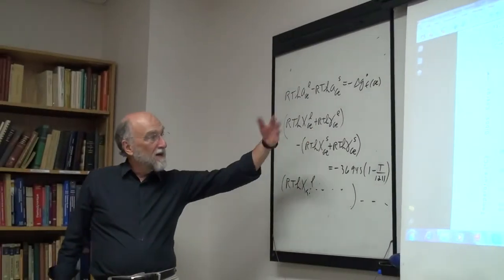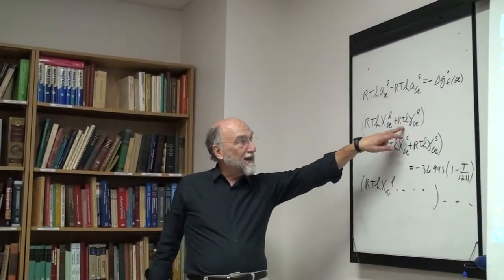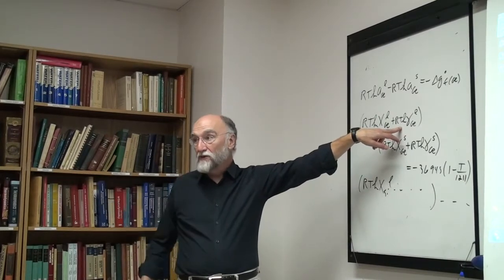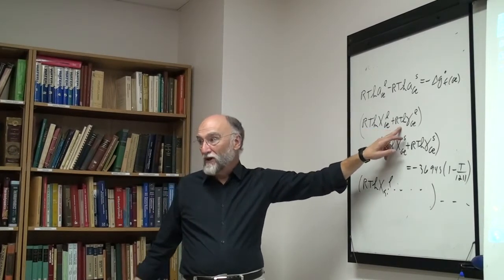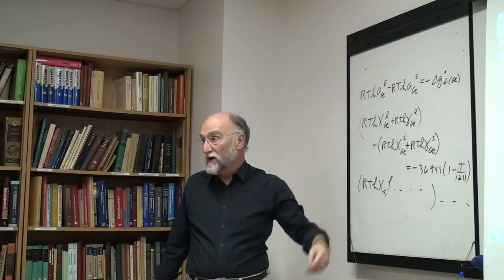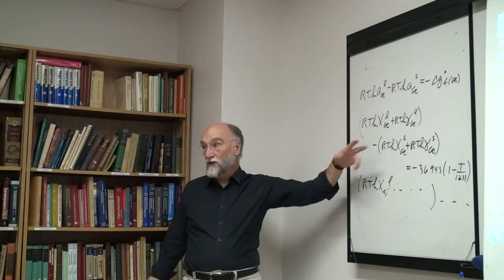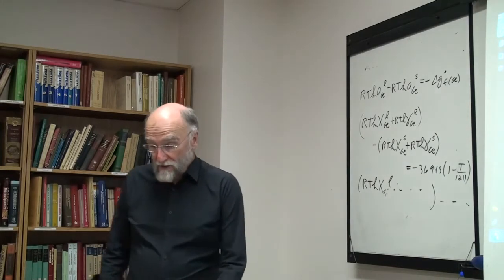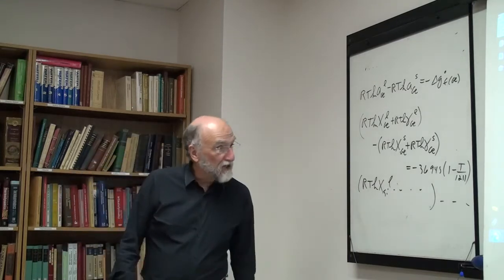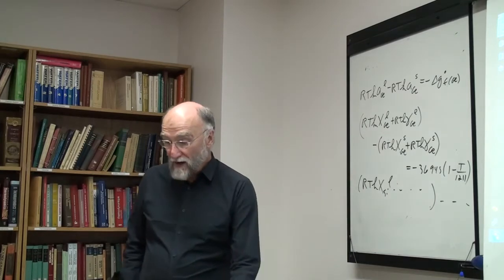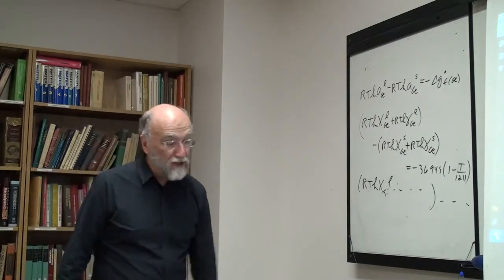The RT log gamma, which is the partial excess Gibbs energy, could be expressed as a power series, a normal polynomial or something, and then you'd have to solve these two polynomial equations in the mole fraction. You could solve them numerically. That's how you do it. That's not the way FactSage does it. FactSage minimizes the total Gibbs energy, but it's mathematically exactly the same thing. But let's just, for fun, assume the general equations you have to solve.